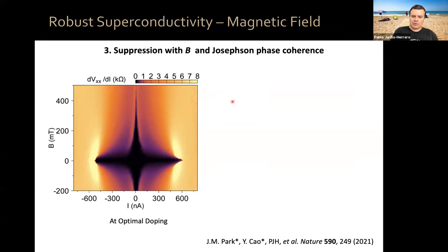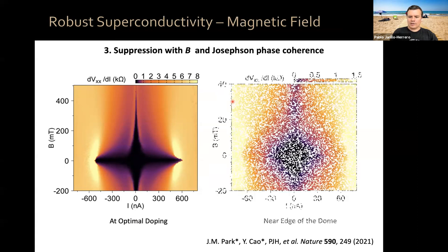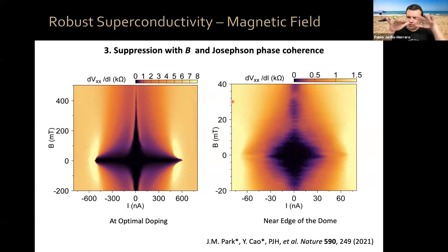And then if, rather than being at optimal doping, you go to a region near the edge of the superconducting dome, where again your system breaks into superconducting and non-superconducting islands, then you can see characteristic oscillations, which are Fraunhofer-like oscillations of your critical current, again establishing that you have some phase coherence, okay? So magic angle twisted trilayer graphene turns out to be a robust superconductor. And by now, I'm aware of at least 3 groups that have reproduced these results.